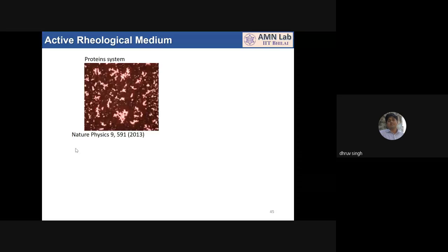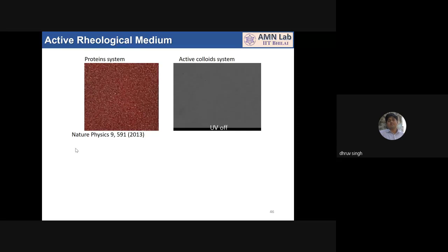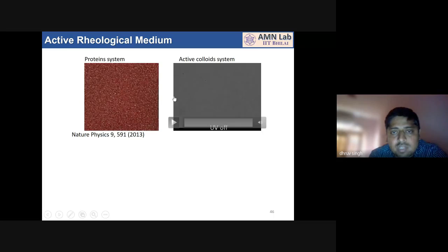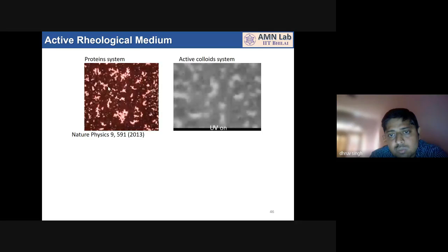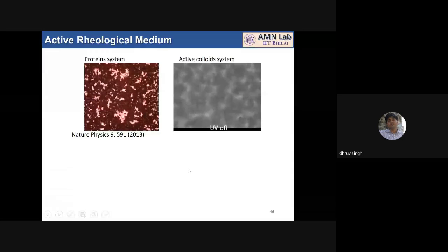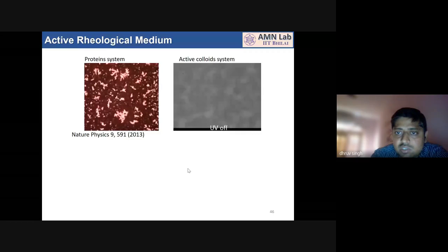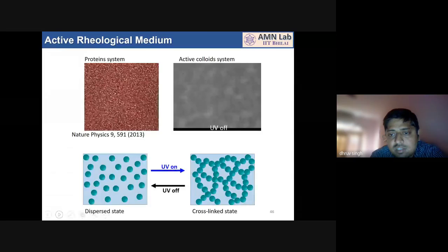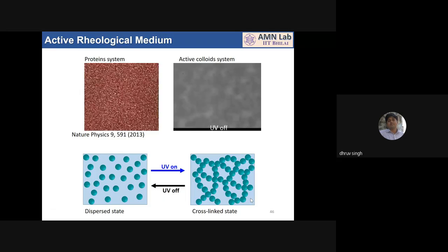And with this motivation, we set up one experiment, and we put a large number of these nanomotors in a system. In the starting, when the activity is off, you can see that they are homogeneously distributed here. So the two look the same in the starting. And when you turn the activity on, you give the light. Basically, light drives the activity. So when you turn the light on to turn the activity on, then our system also forms, because of the dynamic self-assembly, the same approach that I discussed in the previous slides, a cross-linked or gel-like state. And this transition from the homogeneous to cross-linked state in our system too gives rise to a change in the viscosity.